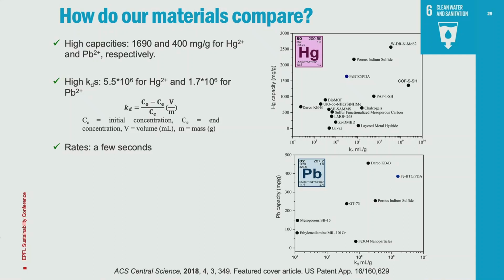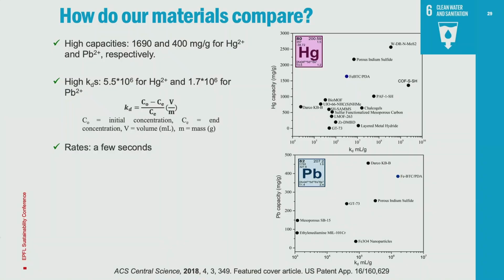Where we really begin to separate ourselves is in the time, the rate at which we're doing the extraction. And the reason is because the material is so highly porous. You can do the extraction very fast, whereas most materials take minutes to hours, ours works in a matter of seconds.